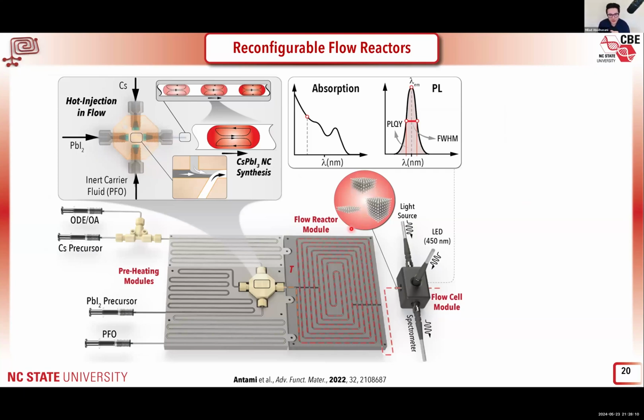So this is why we have this modular design of the precursor lines. Each of these lines or tubing here is embedded within an aluminum module or heating plate, so we can selectively heat the precursors before they are mixed, before they go into the actual reactor section, at a specific temperature. So here is where the precursors are injected, and we can selectively heat these precursors. This is our preheating module, and then this is the actual synthesis module. And at the end, when the product leaves the reactor, we can do in situ spectroscopy to characterize the product.